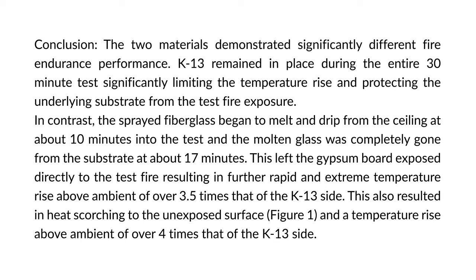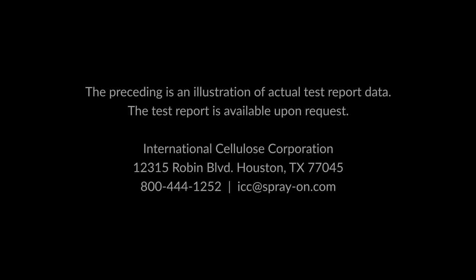This left the gypsum board exposed directly to the test fire, resulting in further rapid and extreme temperature rise above ambient of over 3.5 times that of the K-13 side. This also resulted in heat scorching to the unexposed surface, Figure 1, and a temperature rise above ambient of over 4 times that of the K-13 side. The preceding is an illustration of actual test report data. The test report is available upon request.